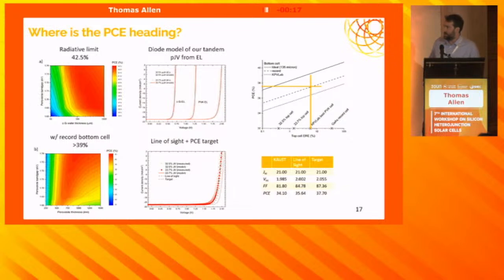So if we were to swap out our bottom cell with a state-of-the-art heterojunction cell, we can imagine an efficiency, a line of sight improvement that will happen very soon, I'm sure, of 35.5%, roughly. And then another thought experiment: we increase the radiative efficiency of the top cell further. The 32.5% cell was about 0.4%. With the additive, it increased to around 1.4%, a very large increase.